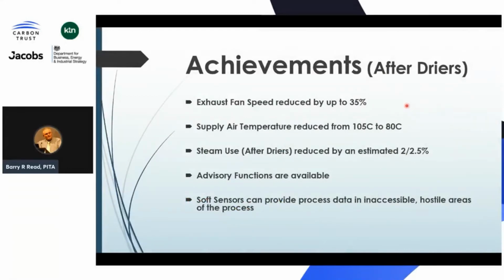So, as I said before, we started on the after dryers, and the immediate results are that the exhaust fan speed has been reduced by up to 35%. So that's 35% less hot air being exhausted to atmosphere. We've reduced the supply air temperature from 105 to 80 degrees C with no loss of drying performance on the paper machine. On the after dryers alone, we're estimating that there's a steam saving of 2 to 2.5%, which, in paper making terms, is quite significant.